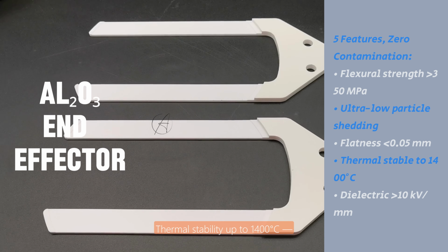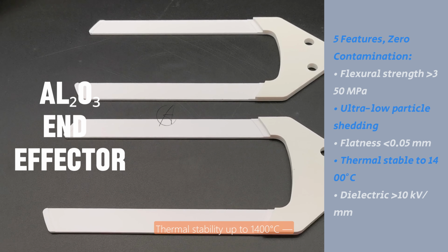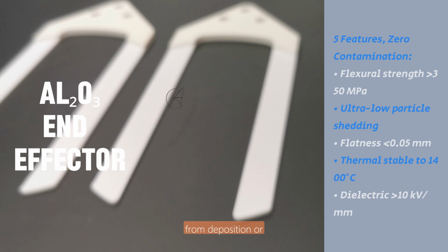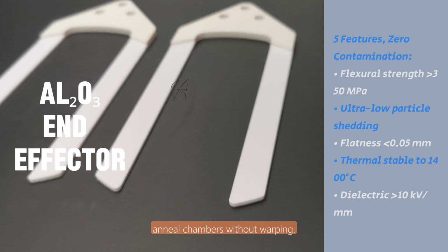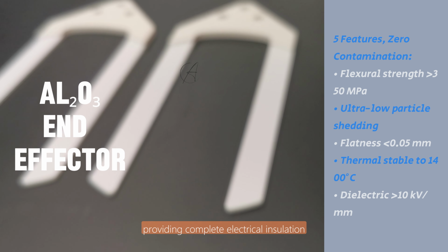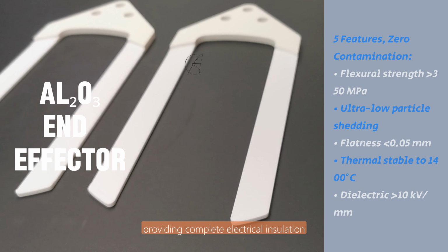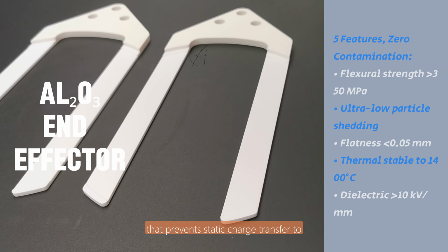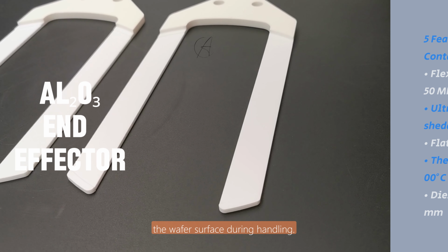Thermal stability up to 1400 degrees Celsius, allowing the arm to retrieve hot wafers directly from deposition or anneal chambers without warping. And dielectric strength above 10 kV per millimeter, providing complete electrical insulation that prevents static charge transfer to the wafer surface during handling.